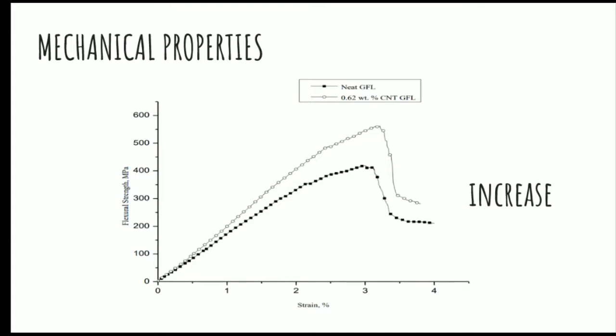Also, the flexural modulus of the carbon nanotube grown composite increased, and this indicates the increase in the interfacial strength between fiber and matrix. In the article, it says that the layer with grown carbon nanotubes creates a bridging effect between the fibers and the matrix that helps restrict the sliding of the layers under tension or compression and thus increases flexural strength. So, we can infer that the failure strain of the carbon nanotube grown woven glass composite also increased if we compare it with the neat one.